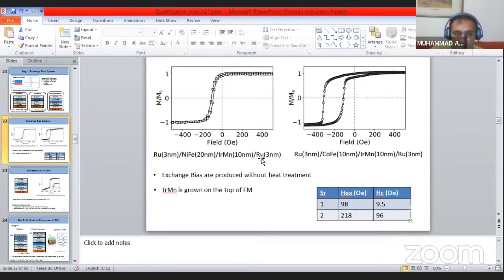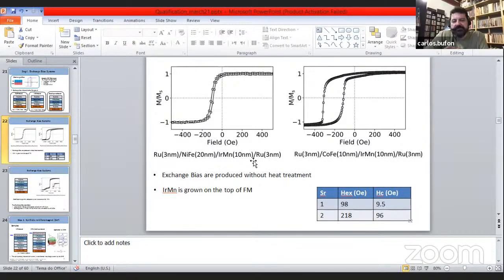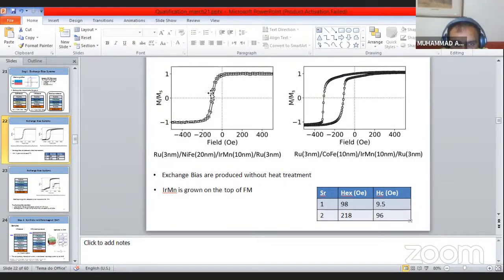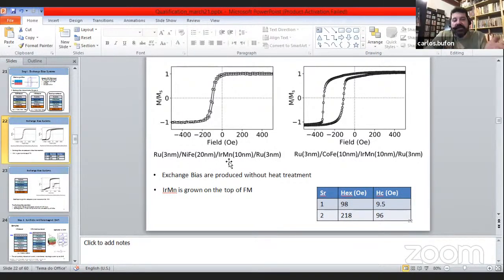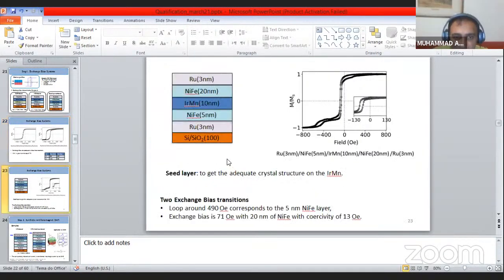This is called exchange bias. Due to this mechanism, this loop is shifted from zero. And this is another exchange bias, with the nickel iron as a seed layer. You see here, this nickel iron has a configuration. If you measure it, it has a 111 plane. If we grow this first and then grow the antiferromagnet, then it has an exchange bias. Without this layer, the antiferromagnet doesn't have an exchange bias. It helps the building of the exchange bias.